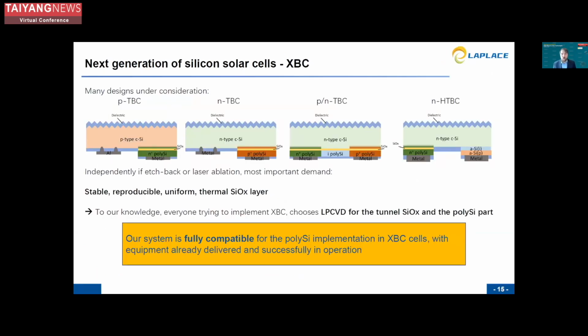When we quickly look at what's next, when we talk about the back contacted solar cells, there are several designs that are currently under consideration in the different manufacturers. We have the P tunnel back contact or the N tunnel back contact, also tunnel back contact with both polarities, or also designs where we get a combination of TOPCon and heterojunction designs. And from what we can see so far from the manufacturers, independently of whether they want to use etch-back or a laser ablation, the most important demand so far is that we want to have a stable, reproducible, uniform thermal silicon oxide, because this is very crucial for getting the back contact design running through a full production line.